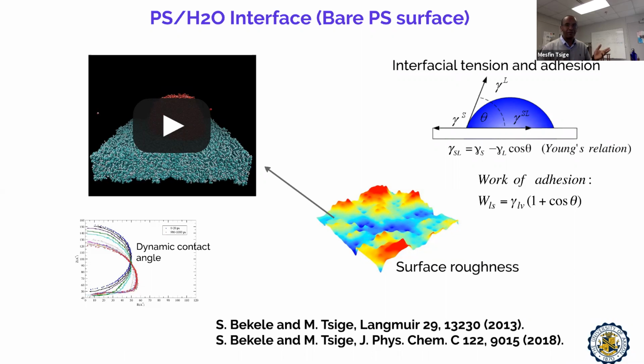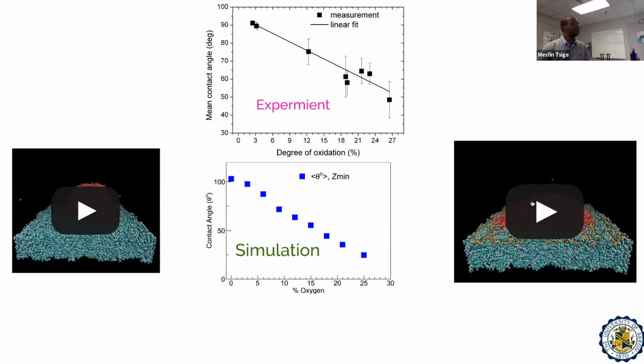So we have varied the degree of oxidation of the surface as they have done in the experiments. In our case, we don't need to do UV radiation. What we do is we go and attach oxygen groups to a selected number of phenyl rings. As a result, we can control the percentage, and we have measured how much the contact angle of water changes with the degree of oxidation. And we see a linear drop as already predicted by the experiments. The error bar in our case is within the size of the symbol.